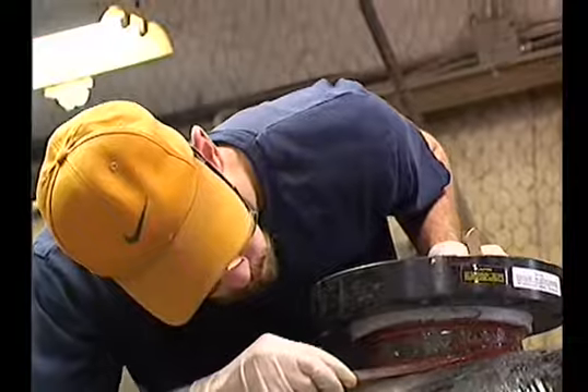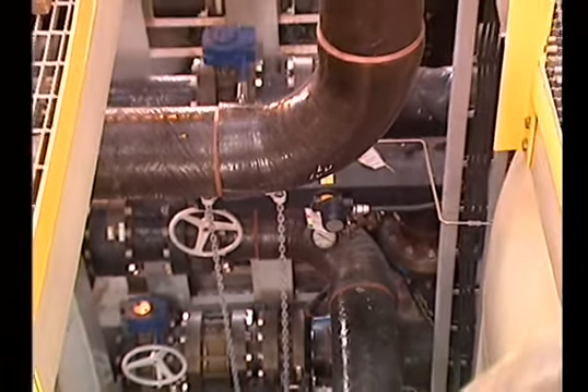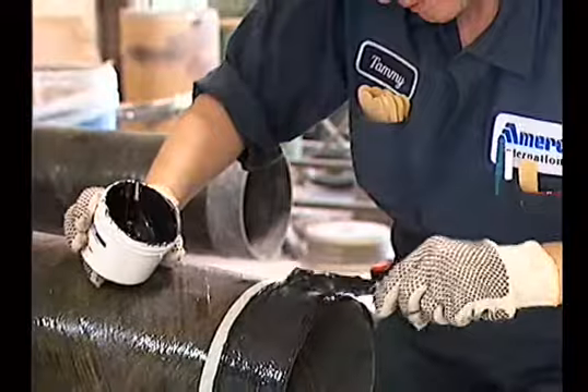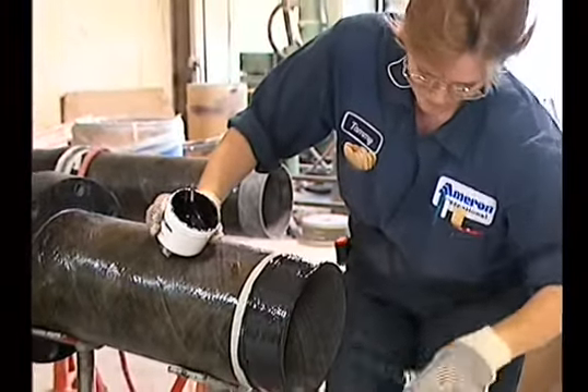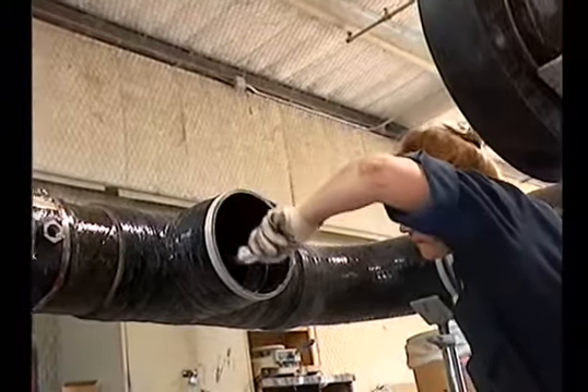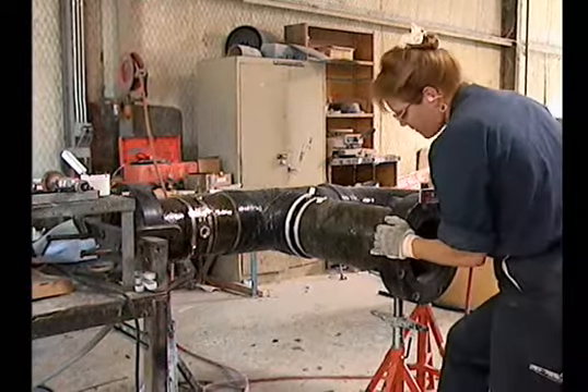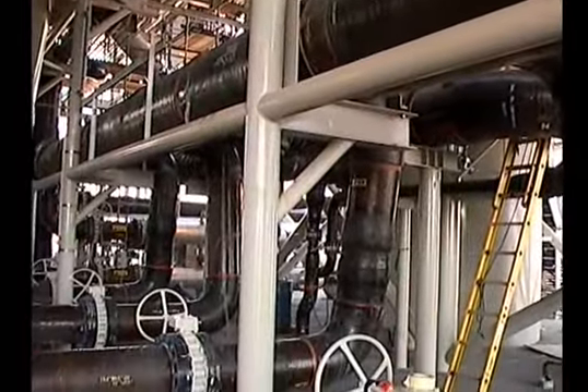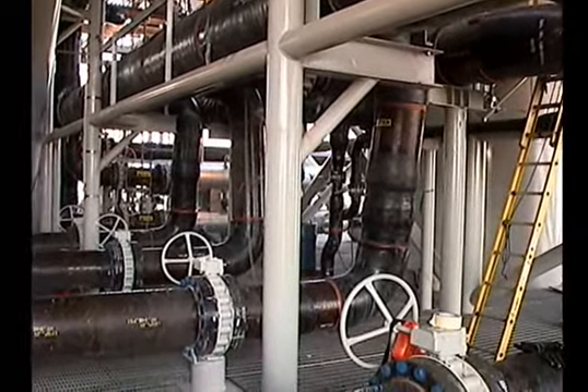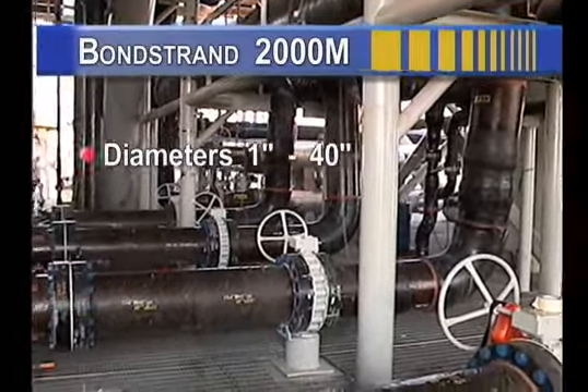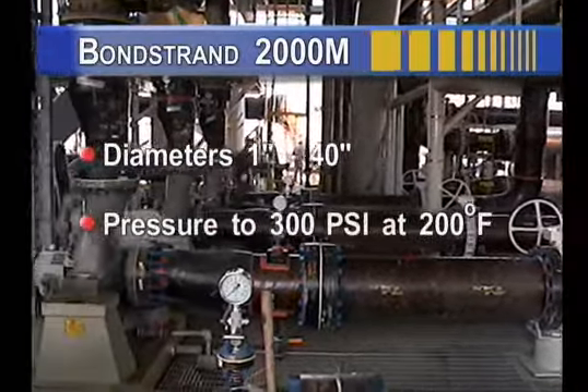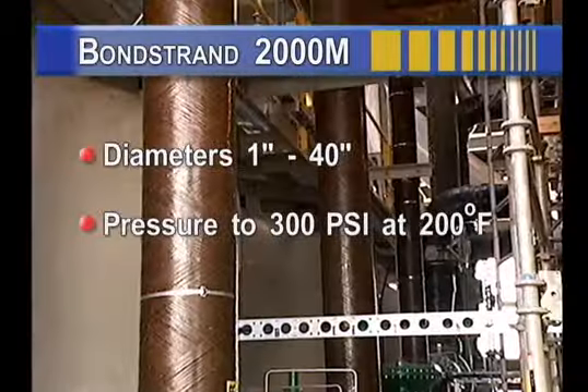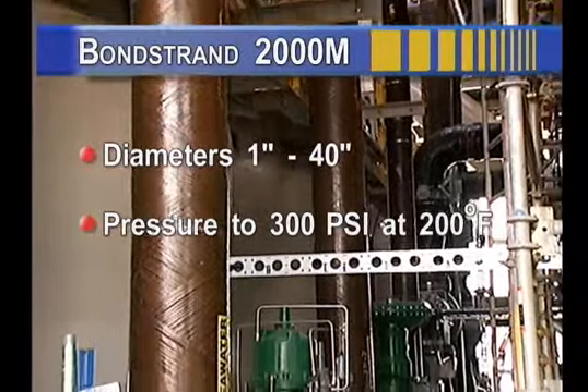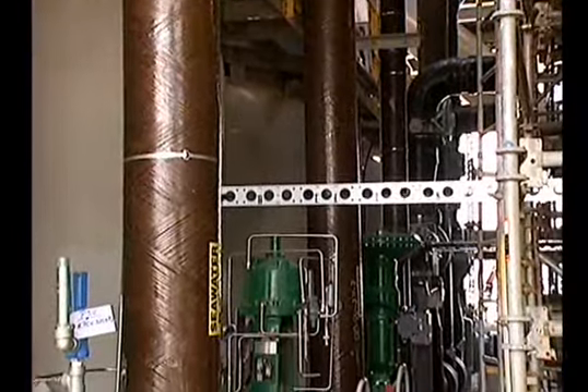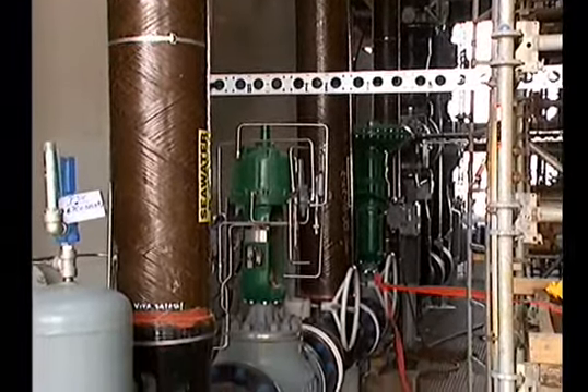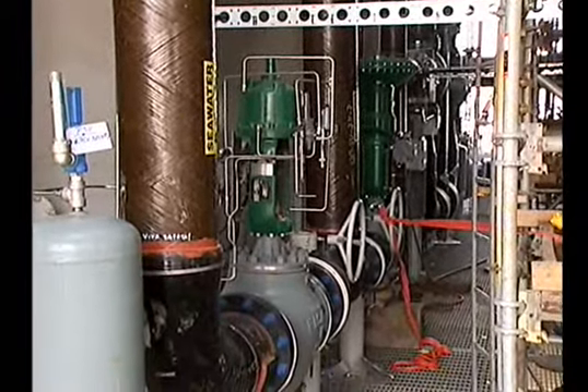Available with flanges or quick lock bell and spigot fittings that have been proven in over 25 years of offshore applications, Ameron Bondstrand piping systems are joined with high-strength adhesives that produce a bond that is actually stronger than the pipe itself. Bondstrand Series 2000M piping for general offshore service is available in diameters from 1 to 40 inches. It is designed to withstand continuous operating pressures of up to 300 psi at 200 degrees Fahrenheit and is typically used in deck drains, cooling water, seawater utilities, potable water, and wet firefighting systems.